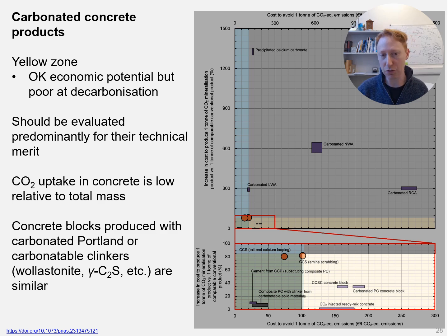The result also shows that the environmental performance of carbonating Portland cement concrete products is about the same as that for carbonating carbonatable clinkers like wollastonite or C2S. The reason is that the CO2 emissions avoided from being able to slightly lower production temperatures down to 1200 degrees, for example, versus 1450 degrees, is not very large compared to the amount of CO2 that is absorbed by the material during carbonation. It is questionable whether we should be pursuing the development of carbonatable clinkers on environmental grounds based on this analysis.